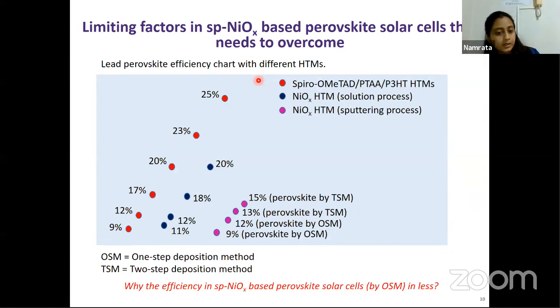Now, emphasizing particularly nickel oxide, we first look at this efficiency chart for perovskite solar cell power conversion efficiencies. Till now, the highest efficiency recorded is based on an organic hole transporting layer in the regular structure, that is spiro-OMeTAD. So we can see that we have 25% power conversion efficiency.